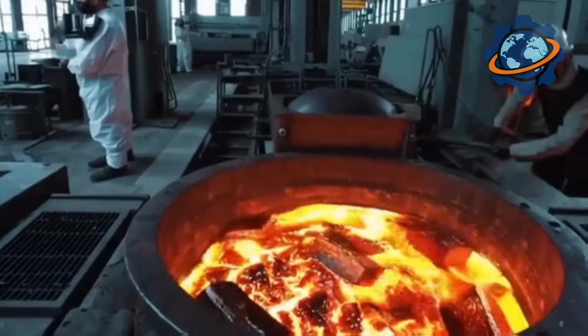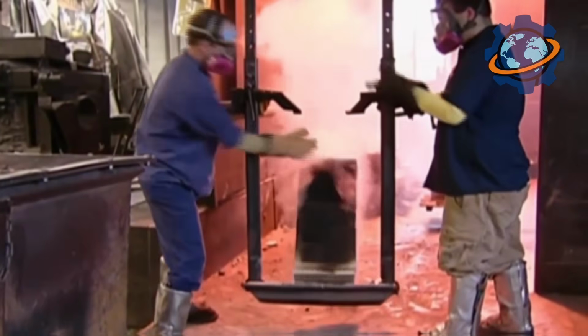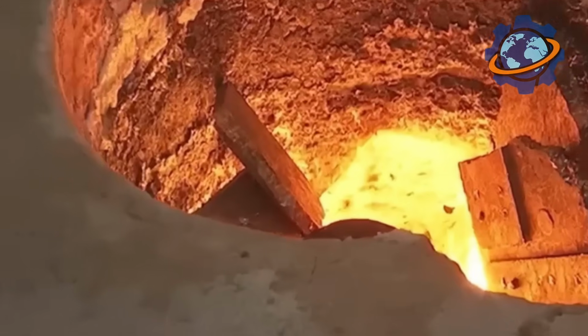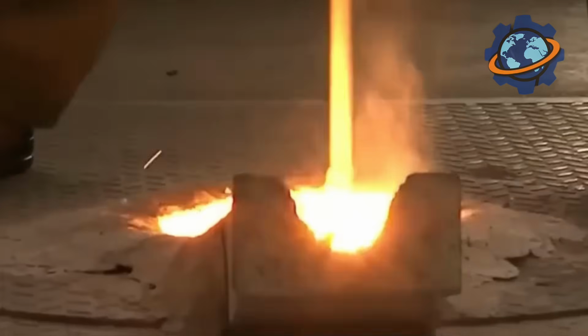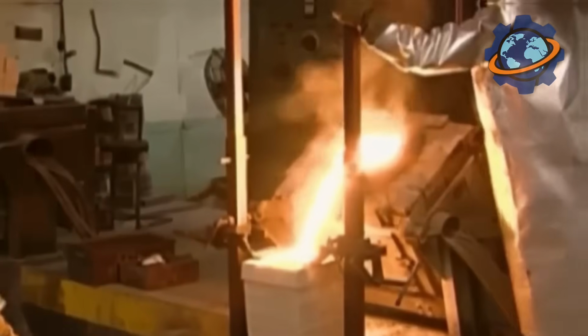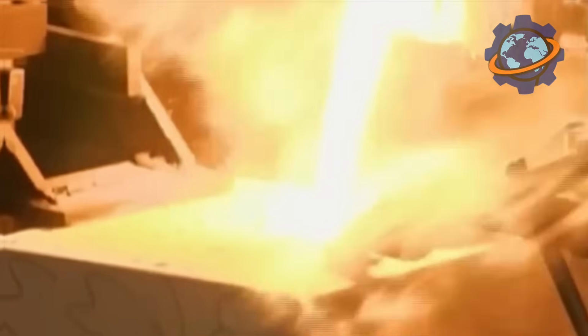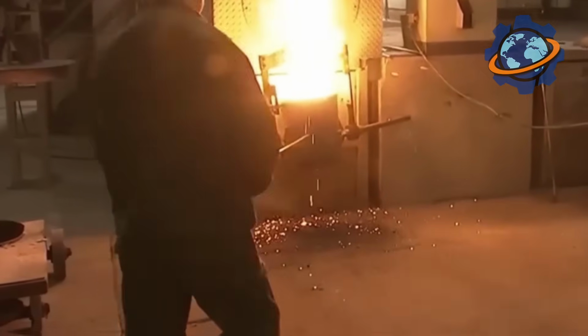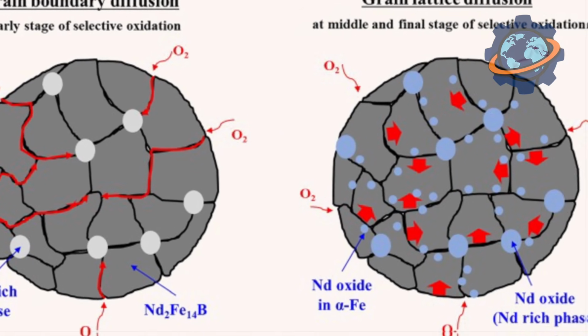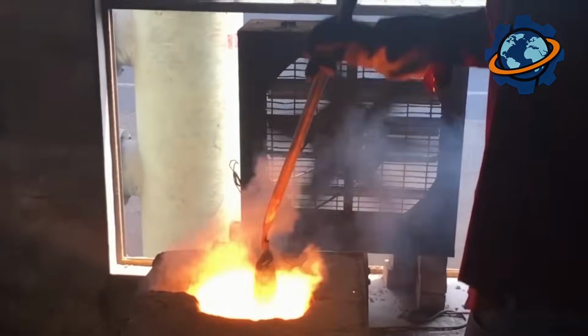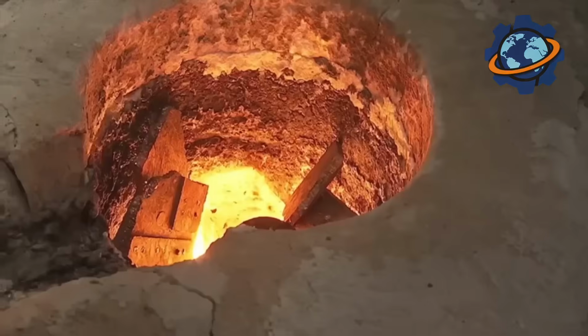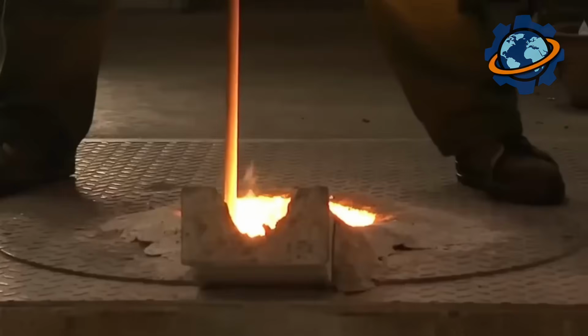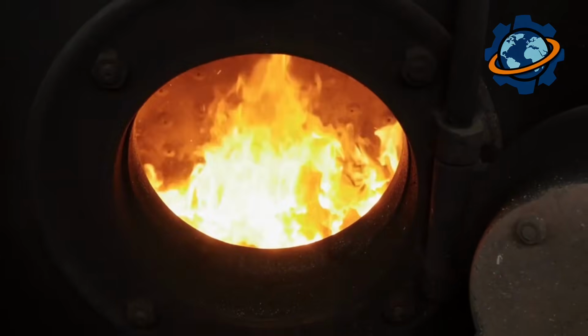The exact composition of the alloy is a trade secret for many manufacturers and varies depending on the desired final characteristics of the magnet. The weighed components are placed in a specialized vacuum induction furnace. The use of a vacuum is critically important as it prevents the oxidation of the rare earth metals and other components at high temperatures. Oxidation would lead to the formation of undesirable phases, which would degrade the magnetic properties of the material. Induction heating ensures rapid and uniform melting of all components, creating a homogeneous melt. The melting temperature in such a furnace can reach over 2,700 degrees Fahrenheit.